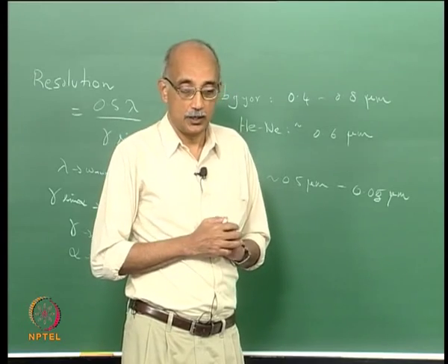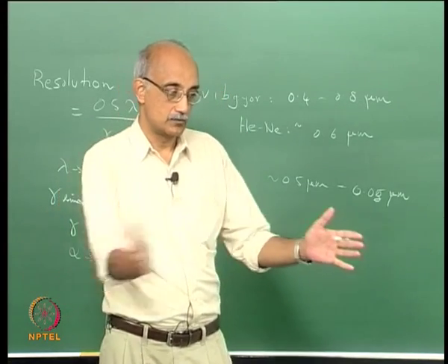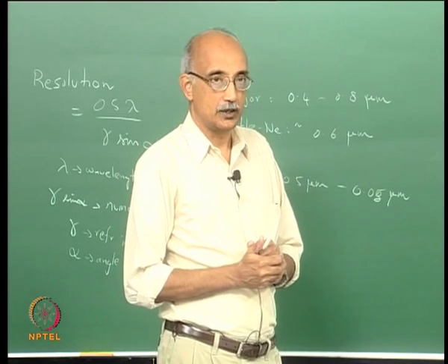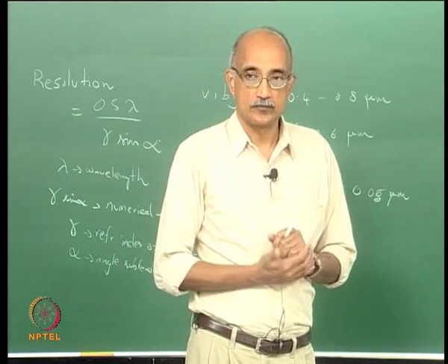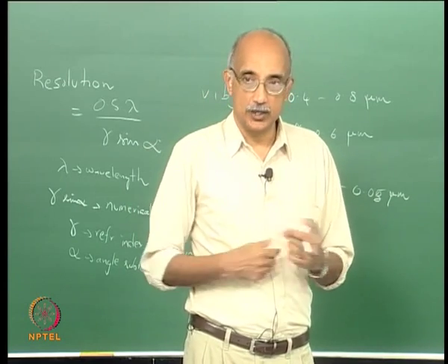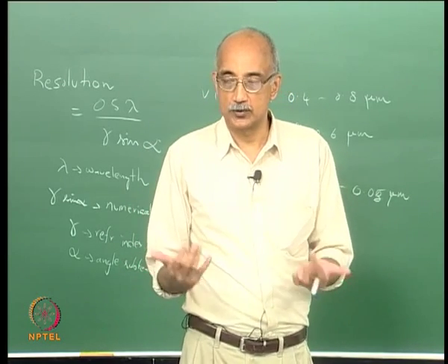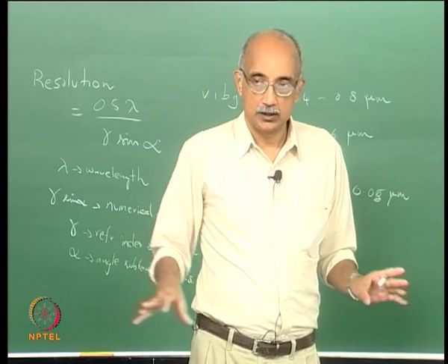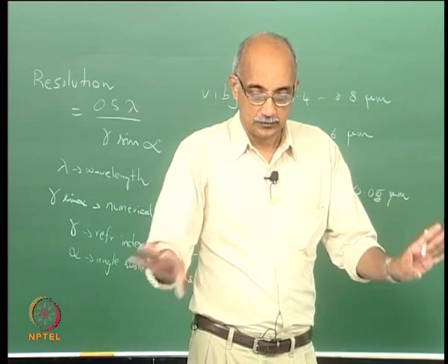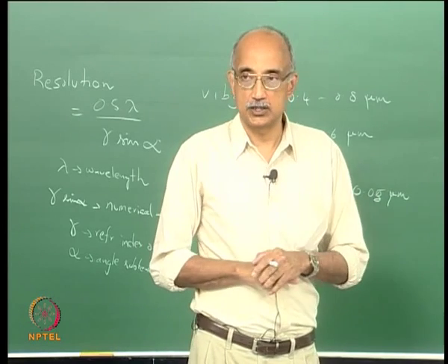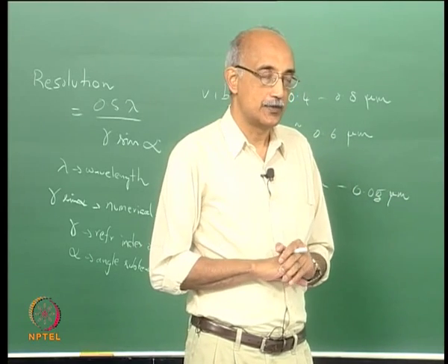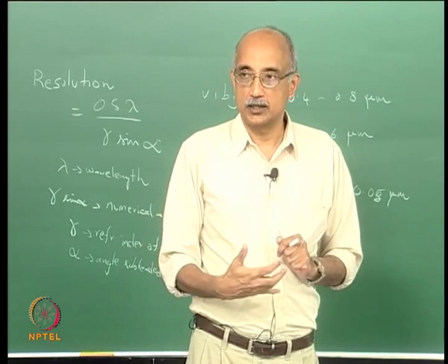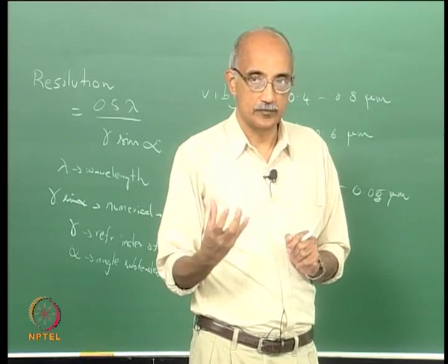On the other hand, if I were really trying to characterize particle distribution on this surface, I would not try to do it in a scanning mode, because I will just get too much noise compared to the signal, the noise being the reflection and scattering that you get from the surface itself. Instead, I will try to grab as refined a picture or image of the surface as possible, and then depend on my processing software to eliminate the noise and give me as clean a signal as possible.